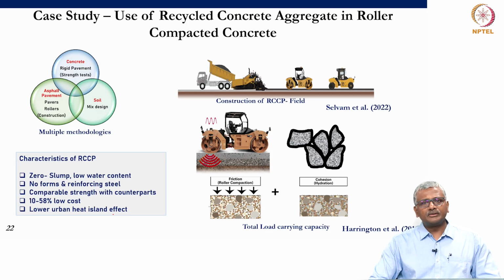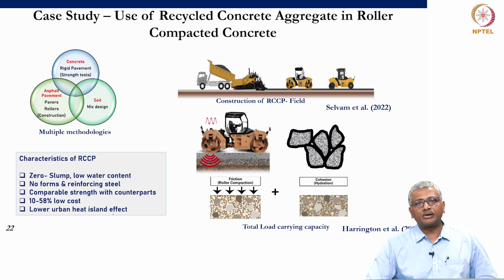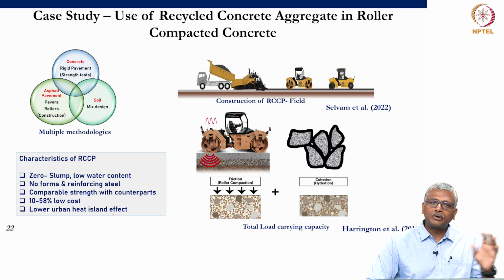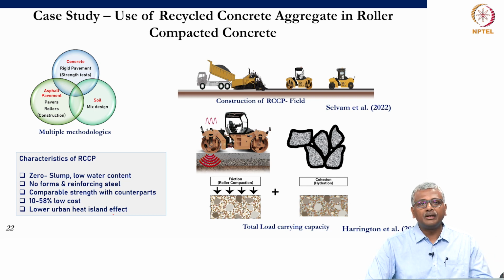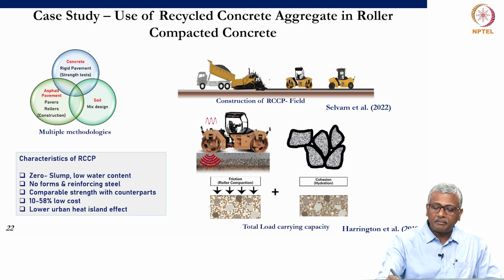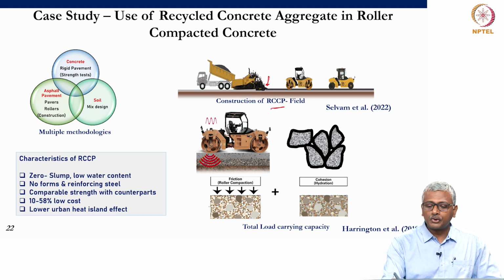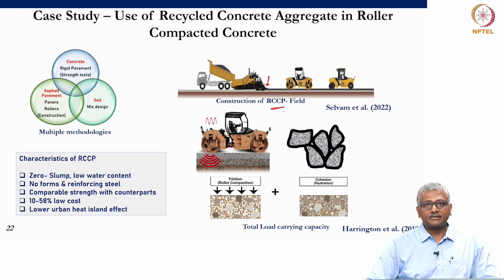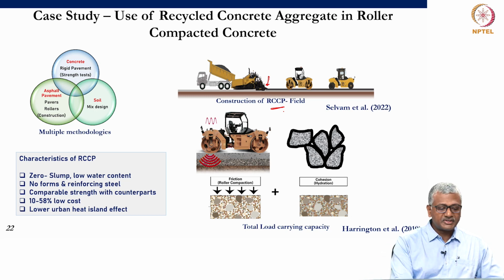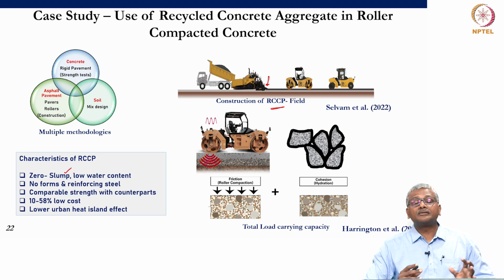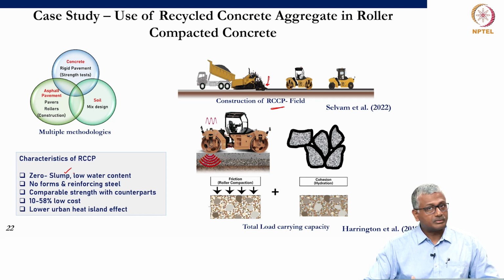Now, let me just show you a case study of the use of recycled concrete aggregate in an application that is at the other end of the spectrum. I talked about flowable concretes, I talked about high workability, but let's now talk about a very stiff concrete such as roller compacted concrete. Roller compacted concrete is where the concrete is dumped and then compacted with rollers. Primarily, it's used for roller compacted concrete pavements, right? Roller compacted concrete pavements basically are zero slump. That means workability is zero or very harsh mixes, water content is low.